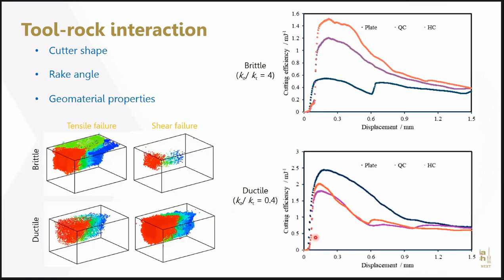We also look at the impacts of the material properties. If you have a more brittle material versus a ductile material, we can track, when we scratch at the surface, how many of the particles will be broken in tensile failure versus shear failure. If we have a brittle material, most of the failures will occur by stretching the particle-to-particle bond and breaking them in tensile modes. While if we have a ductile material, like Play-Doh to an extreme case, most of the failure at the contact level will be dominated by shear.